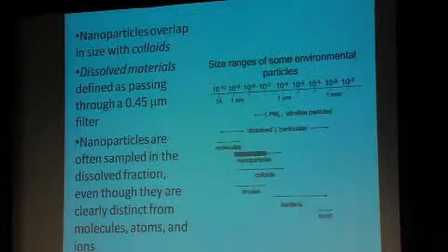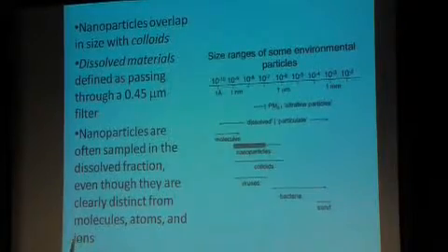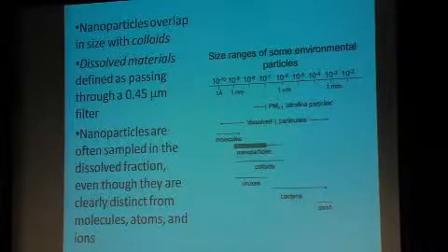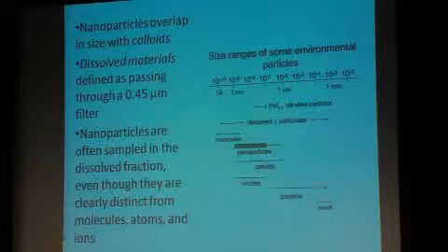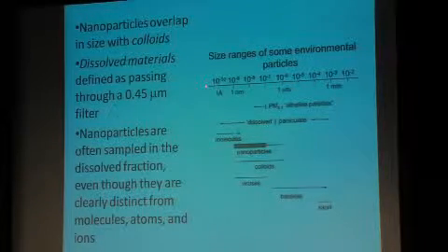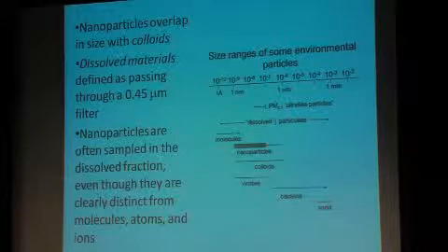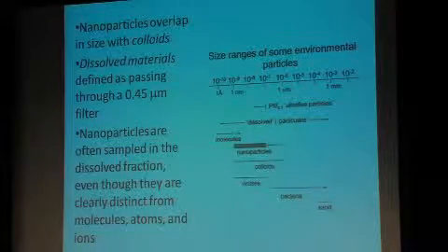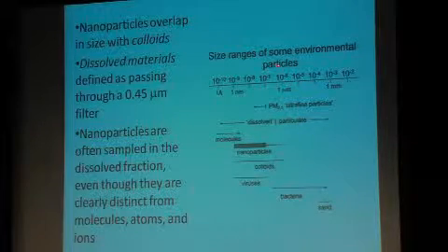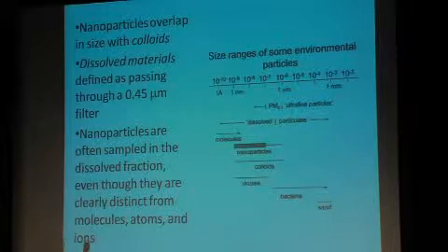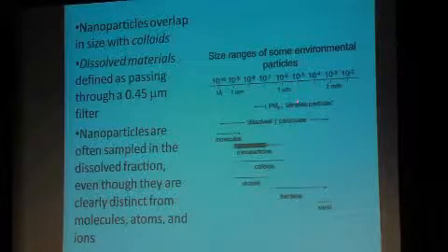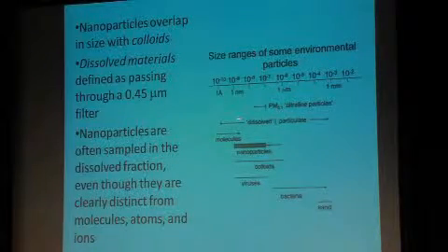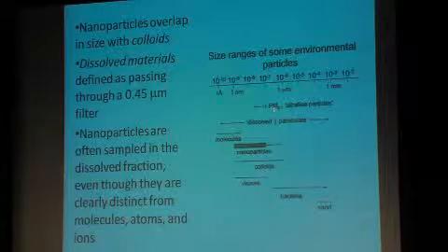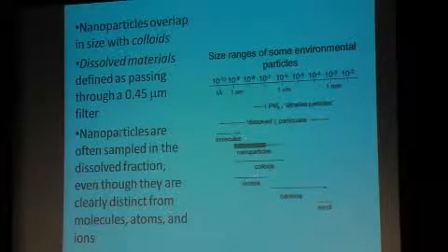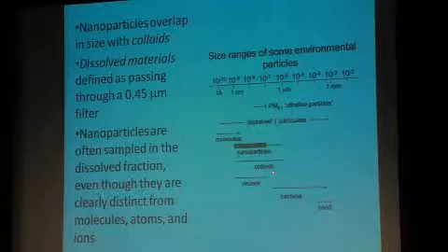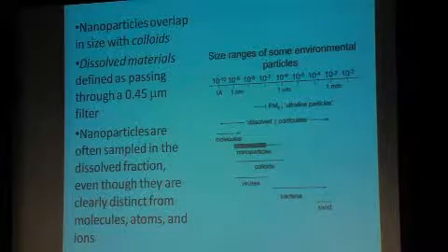We've seen this in a different format. Let's look at how an earth scientist would look at nanoparticle size. Here we've got the sizes of different particles in nature. An angstrom is about the size of a bond or several bonds, depending upon exactly what you're talking about. Nanoparticle, if you look just linearly, is about 10 of that. Ultrafine particles are about 0.1 micron. Dissolved versus particulate is 0.45 micron. Molecules, nanoparticles, colloids, and viruses all tend to be in the dissolved fraction or at the boundary with the particulate.